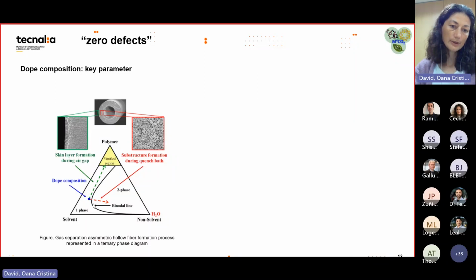The one on the left is one phase, so everything is miscible, and the polymer is liquid. The two-phase region is where you actually form the coagulation of the polymer and then the pores inside this layer. So we want to be close to this phase change, close to the coagulation of the polymer. This is where we start with the dope, with the blue line. And then we have to define where this boundary line is for a new polymer.